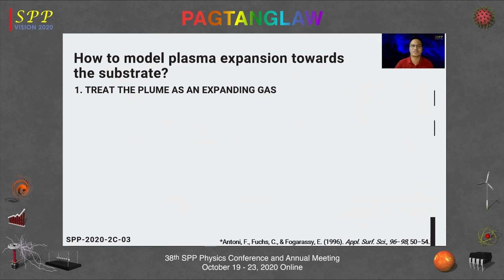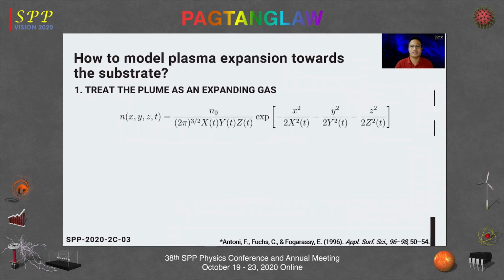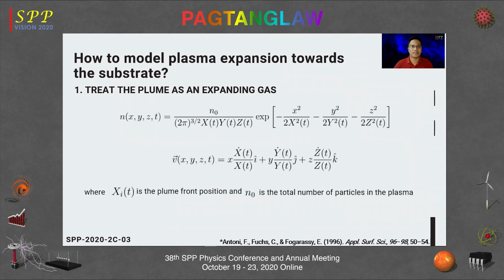Now, how do we model the expansion of plasma plume towards the substrate? We can treat the plasma plume, the laser-produced plasma, as an expanding gas. This is from a 1996 model wherein the solution for the density and velocity is given by these equations, where capital Xi, capital X, capital Y, and capital Z is the plume front position, and N naught is the total number of particles in the plasma. The product of the density and the velocity gives us information on the material flux anywhere in space and time.